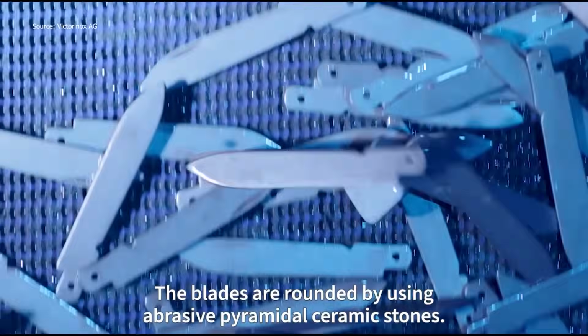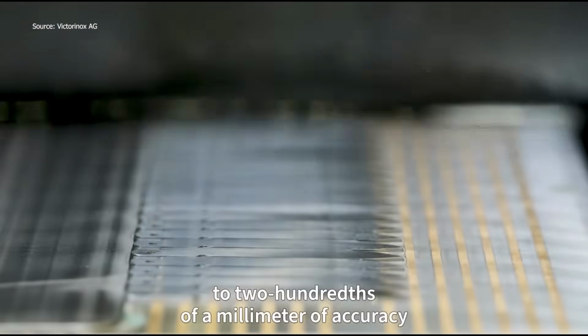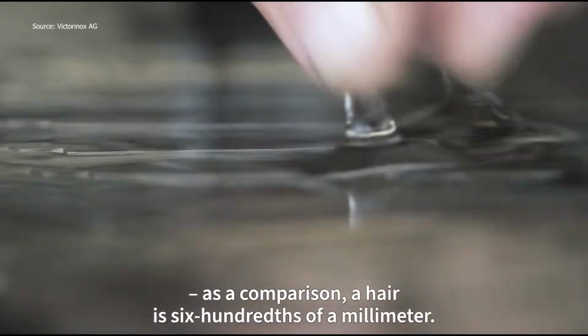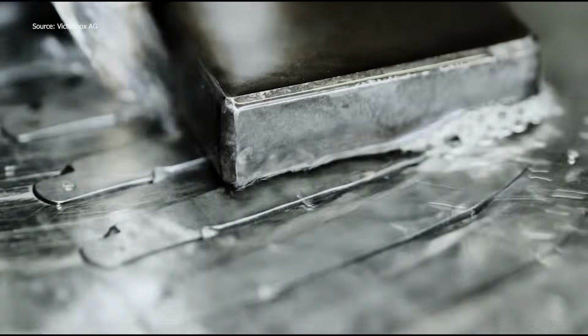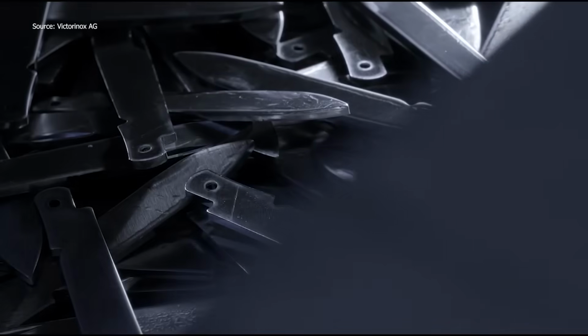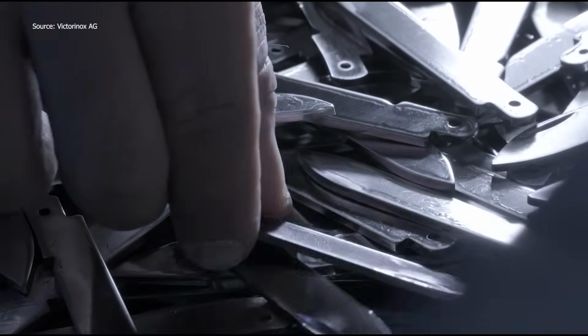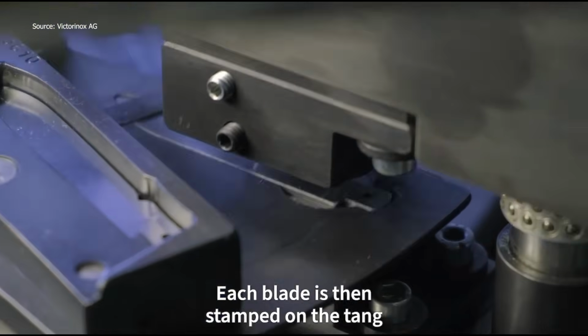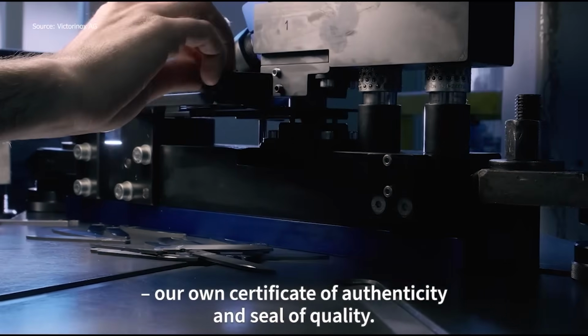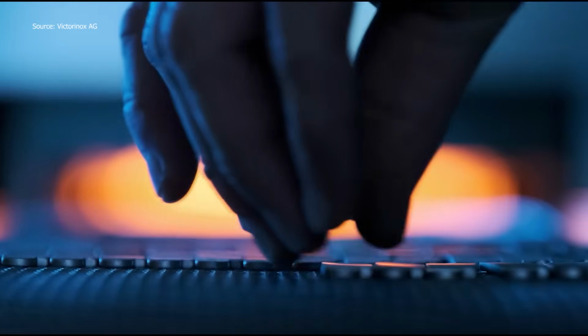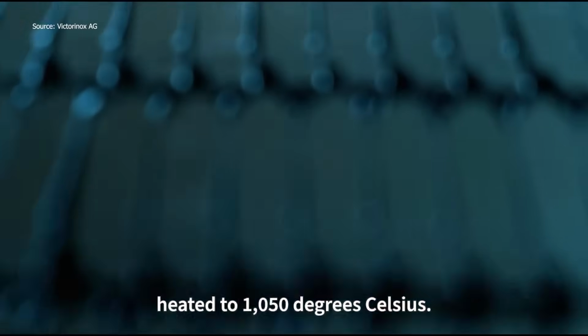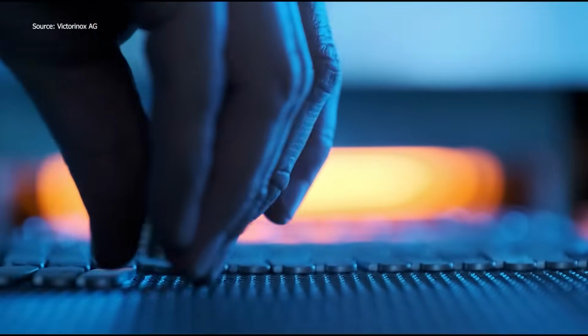Every Swiss Army knife begins with raw steel, 95% of it recycled. Blades are stamped from 3 mm thick strips, using 60 tons of pressure, then rounded with ceramic stones to 0.02 of a millimeter. That's tighter than a strand of hair. After stamping, blades are hardened at 1050 degrees Celsius in massive ovens. Precision grinding gives them a sharp, durable edge. Each is then stamped with the Victorinox logo, a seal of authenticity and quality.